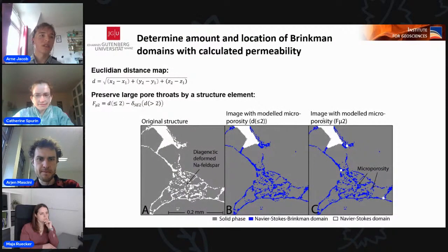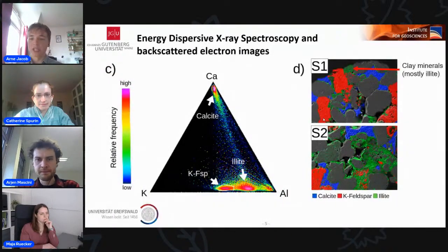So the next issue was, how do we get this permeability information of the clay into our micrometer scale synchrotron data? Well, since we know from backscattered electron microscopy, it was the image I was showing before, that we have a lot of illite hidden in the pore throats, we should be able to model them into our pore throats. By doing so, the modeled clay minerals in each pore throat with a diameter of 2 voxels or less are assumed to contain illites. We did this by using the Euclidean distance maps.